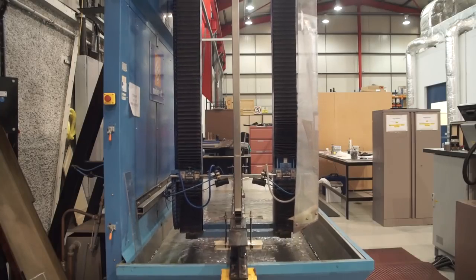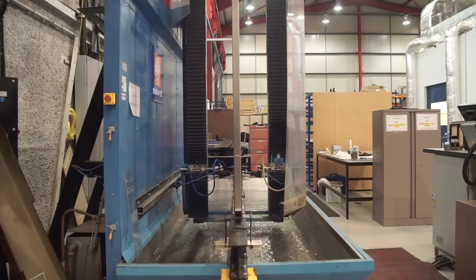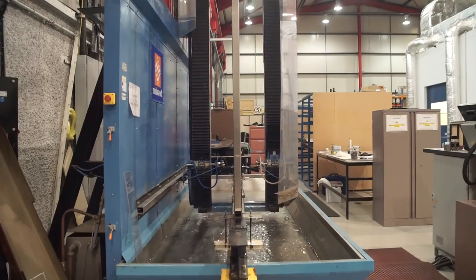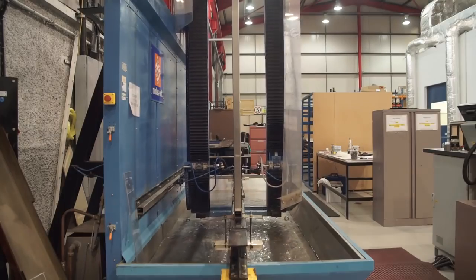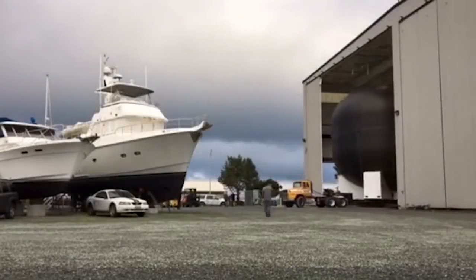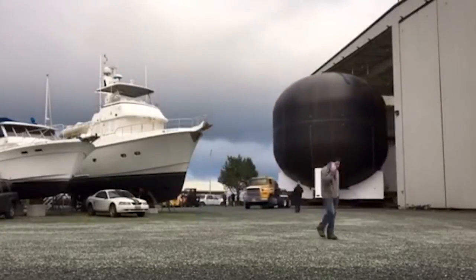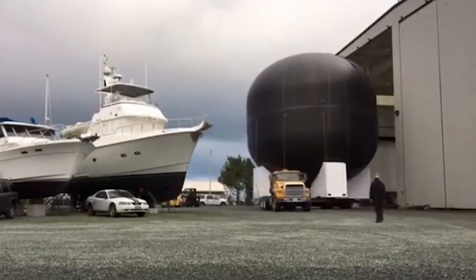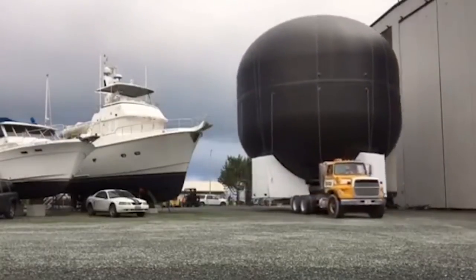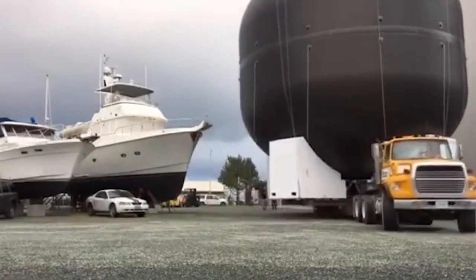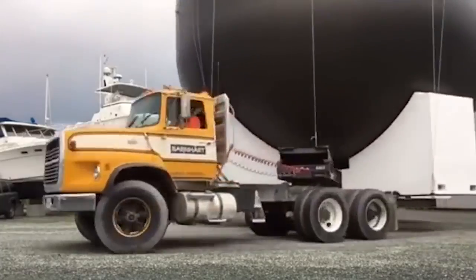These voids are an even bigger concern for this application, because the biggest problem for the material is cryogenic fuel leaking through microcracks and voids. Looking at the outside of the tank, I would say with a fair bit of certainty that the tank was made in two halves that could fit in an autoclave, and was then riveted and welded together, which I would imagine will be removed for the final version, as this just creates weakness in the structure. But this is all guesswork.